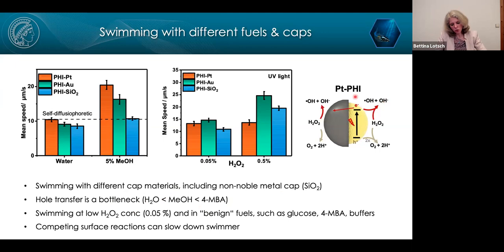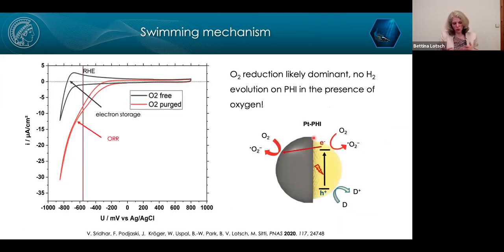Now, we also noticed that competing surface reactions, like shown here, where we have a reaction on the platinum side, so hydrogen peroxide decomposition, and also light-induced hydrogen peroxide decomposition at PHI, can compete and slow down the particles. That is, for example, shown here, where the platinized system is actually slower than the gold system, where hydrogen peroxide decomposition is not as efficient. And that is something we need to keep in mind when it comes to solar battery type swimming, as I show you in a minute.